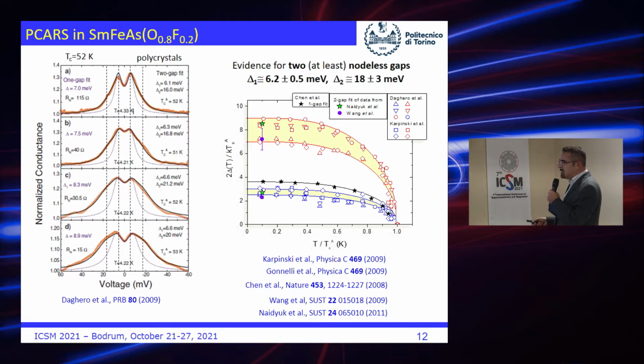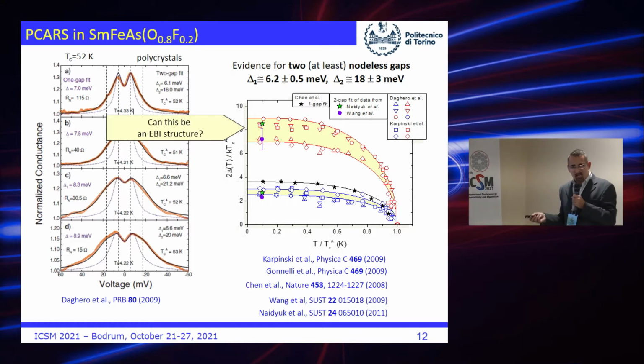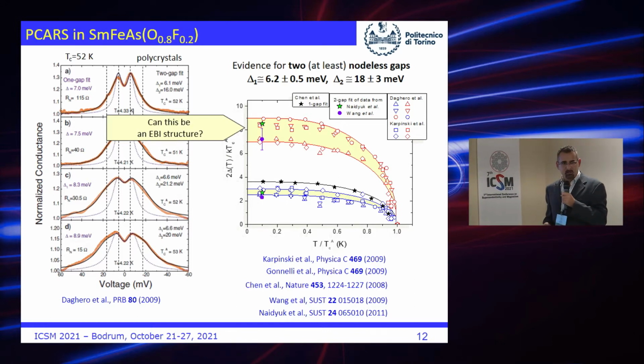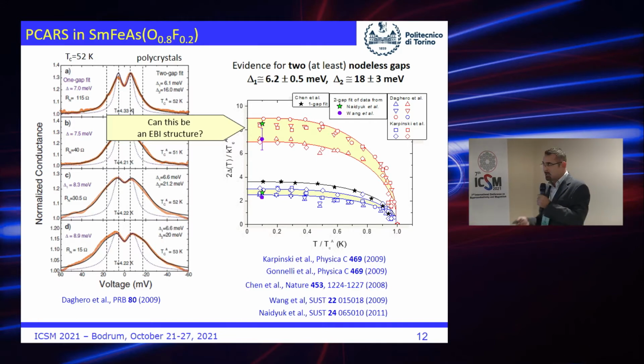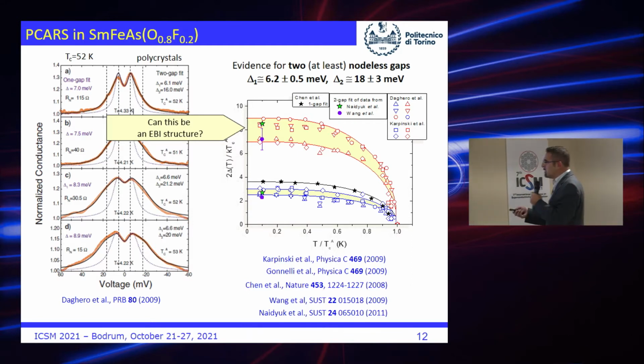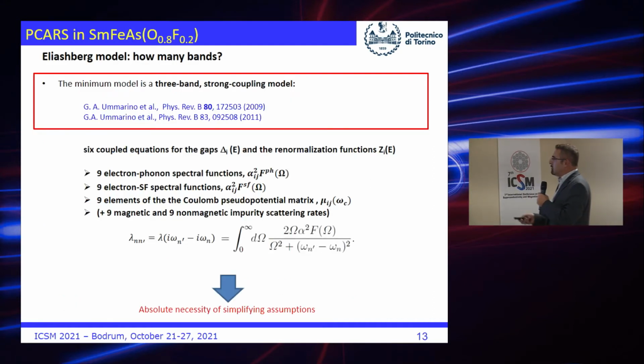But you see that the uncertainty is huge, especially here. As far as the small gap is concerned, it's more or less okay. But the large gap seems to be very large, with a large uncertainty. So we asked ourselves, is that really a gap, or are these electron-boson interaction structures? Well, to answer this, we have to solve the Eliashberg equations. Actually, we already knew that the most likely boson was a spin fluctuation, so we take this into account. We wanted to see whether the spin fluctuation boson can provide these structures here, or instead these are really gaps.